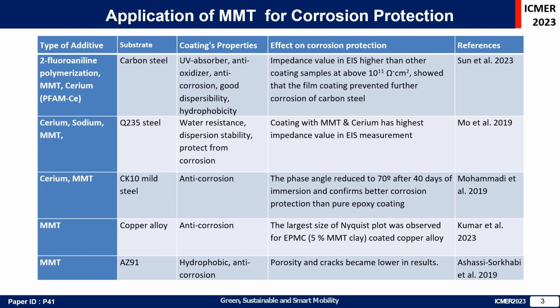And lastly, Ashassi-Sorkhabi used MMT on AZ91. Their coating shows hydrophobic and anti-corrosion properties. The results show that porosity and cracks become lower.